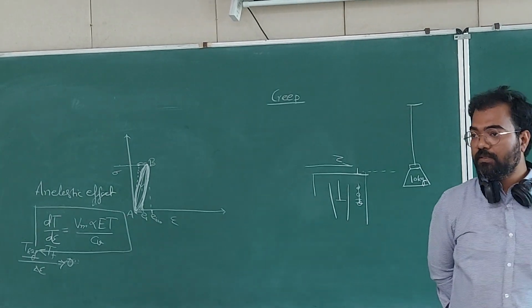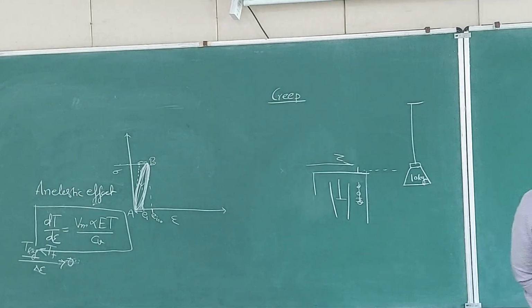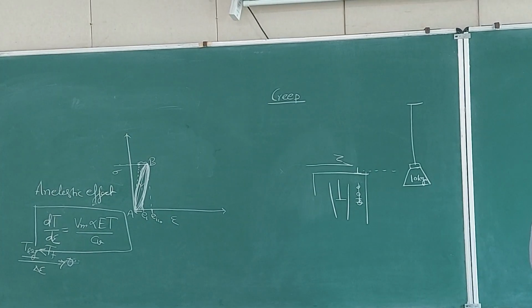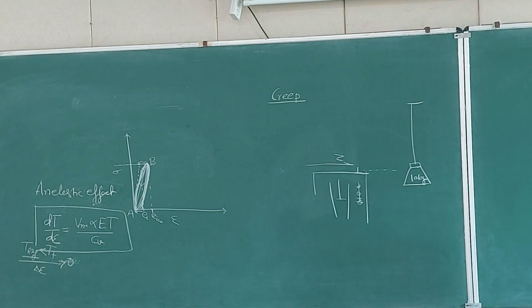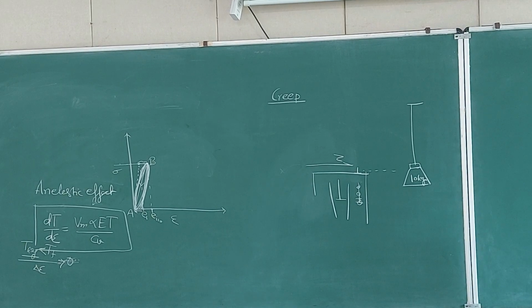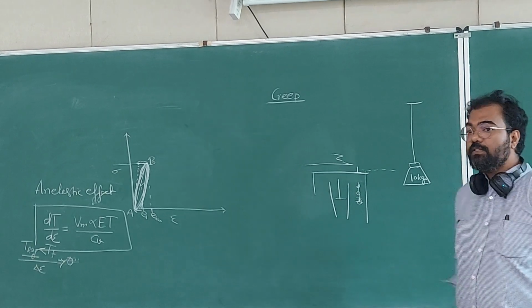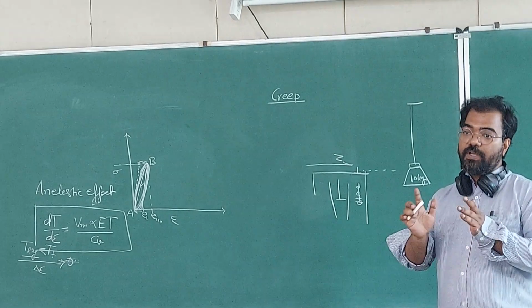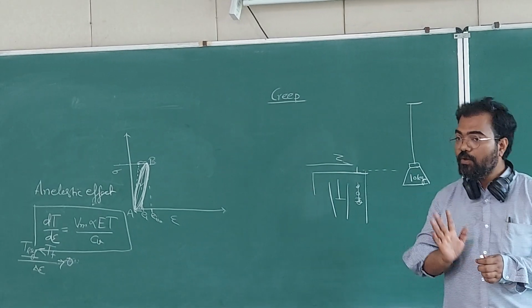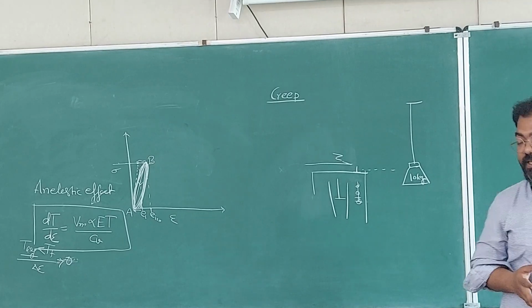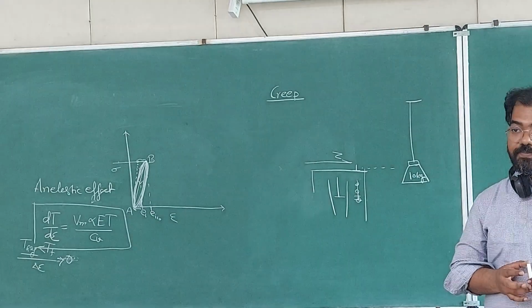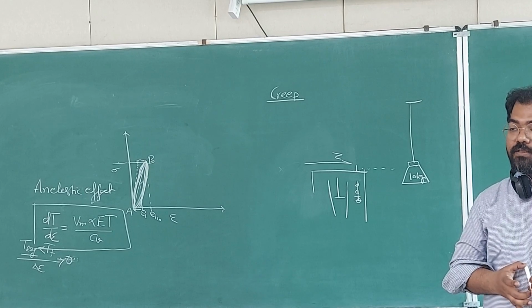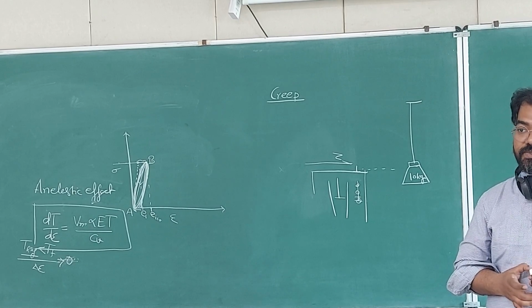Yes. So to isolate the effect of time in comparison to strain hardening effects, so time dependent and time independent phenomena both can happen simultaneously. Okay, and both do happen simultaneously. But in order to dissociate these two and see isolated the effect of time only, you need to apply a constant force. Okay, ideally you should apply constant stress, and there are machines which can apply constant stress,